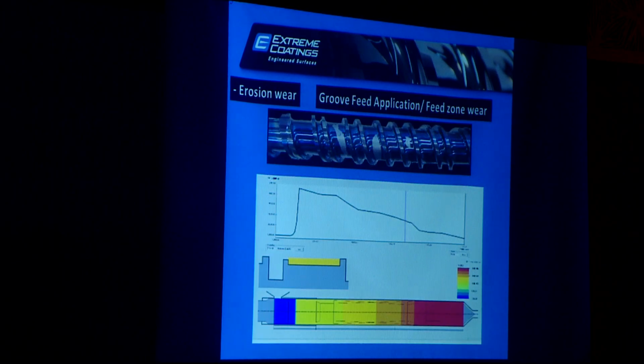The fourth wear is erosion wear. This phenomenon is mainly witnessed in people who are using groove feed extrusion lines. Near the feed pocket, the groove feed helps to feed the material a lot. But at the same time, it creates lots of back pressure on the sidewall of the flights. So instead of the screw wearing out from the top, it starts wearing out from the sidewall. And then eventually, the feed capacity gets reduced and you start getting lower and lower output.